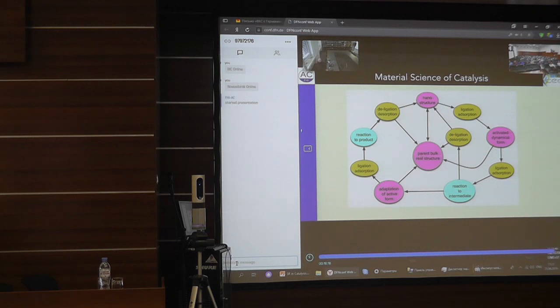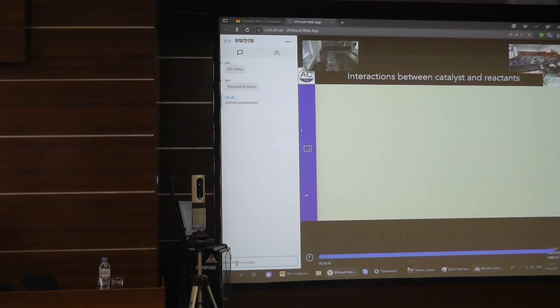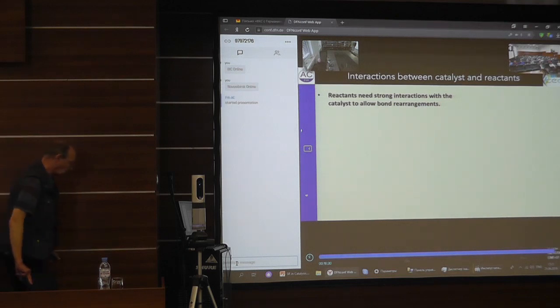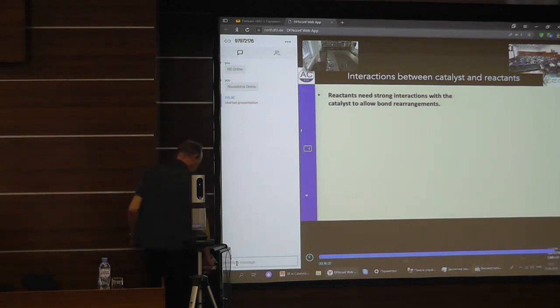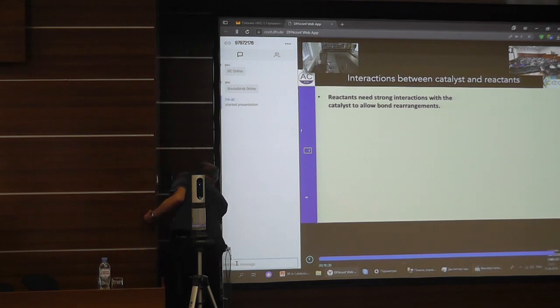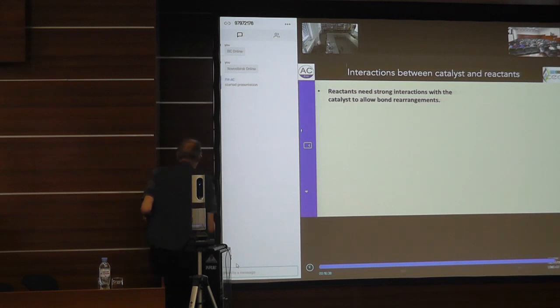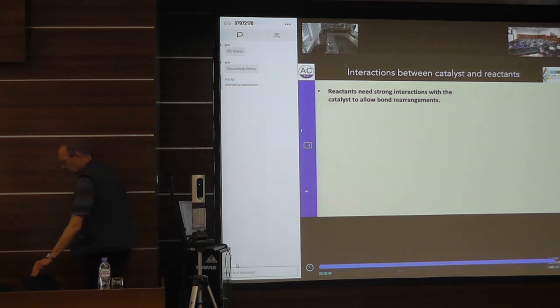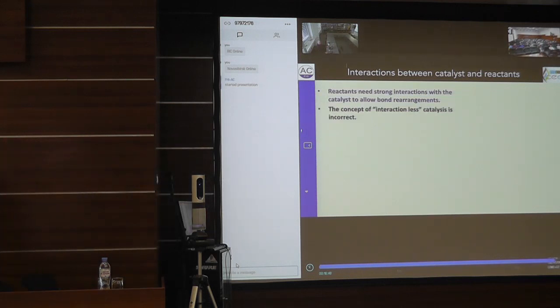So, what kind of interactions between catalyst and reactants do we have? Reactants usually need strong interactions with the catalyst to allow bond rearrangement. Think about dissociation of oxygen, hydrogen, and nitrogen. You have to overcome huge barriers in order to break these molecules apart. That means weak interactions will not be sufficient. You know this very well from the concept of the Sabatier volcano and all these related concepts. The concept of an interactionless catalyst is thus incorrect.